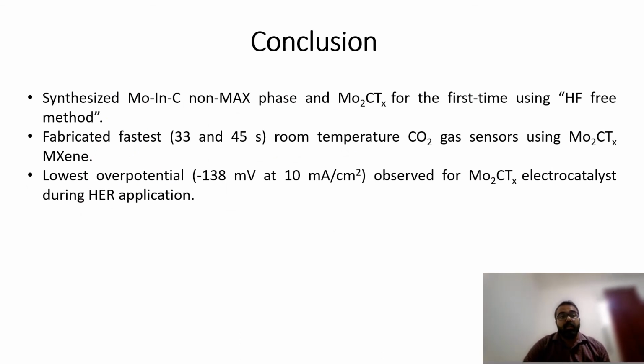So coming to the conclusions, we successfully synthesized molybdenum indium carbide non-MAX phases and prepared Mo2C MXene from these non-MAX phases for the first time using a HF-free method, which is an eco-friendly method of producing MXenes. Then we have fabricated gas sensors which detect carbon dioxide with fast response and recovery times in the order of 33 and 45 seconds at room temperature using molybdenum carbide MXene. And then we have successfully fabricated an electrocatalyst with a lowest overpotential of minus 138 millivolt at a current density of 10 milliampere per centimeter square, which is the lowest reported value for molybdenum carbide MXene electrocatalyst.